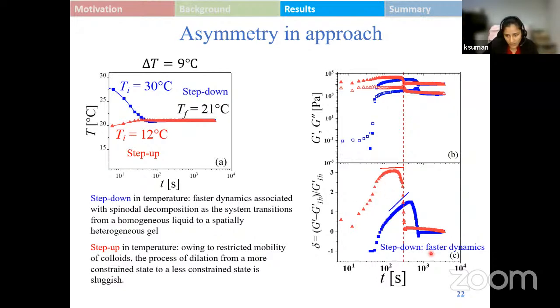We believe that the faster dynamics in the step down experiment is because we are coming from a very less restricted state, which is the liquid state, whereas in the step up experiment, we are coming from a very constrained state to a less constrained state, and therefore the dynamics become more sluggish as compared to the step down experiment. But ultimately, the final state is identical in both approaches.